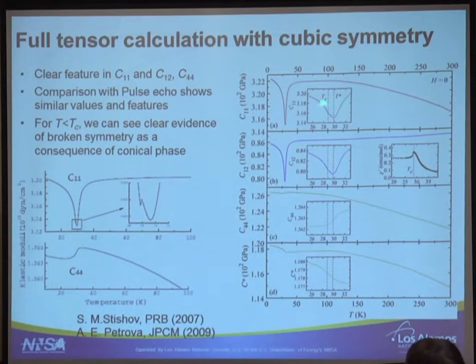And what we see is that at the transition, we see a huge softening of the C11. And what this is telling us is that this transition has to do with orbital fluctuations, if you want, and not shear pairing, as you could say. If you had a hardening transition, you would have shear pairing between the orbitals, and you don't see a big thing here. And this is consistent with ultrasonic measurements done in MnSi back in the 80s. And here I'm showing new results, but this was known for many years.